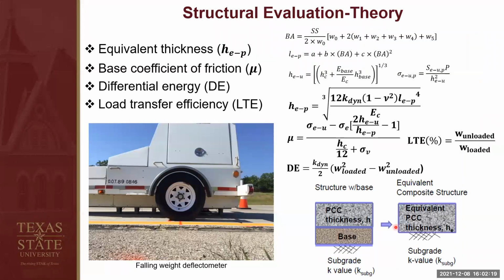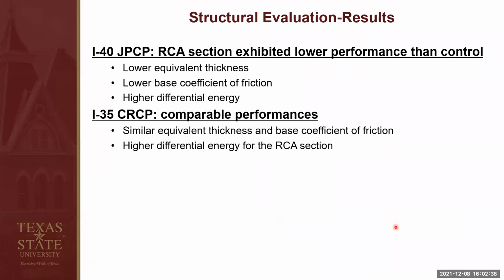And then we did some FWD work. We evaluated equivalent thickness, base coefficient of friction, differential energy, and load transfer efficiency based on some theories we developed at Texas A&M University. For our results, I'm just showing the conclusions. As you can see, for the I-40 JPCP, the RCA section showed lower performance than the control.